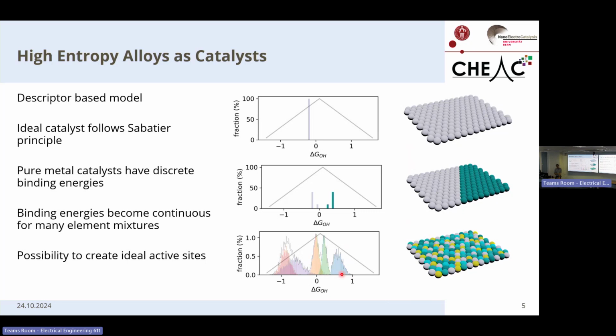So essentially, you think that for designing high entropy alloys for a given reaction, you should always include the state-of-the-art catalyst. Say for oxygen reduction, you should always include platinum. For CO2, maybe gold. Not necessarily. If you get a platinum-free catalyst, you could potentially find a high entropy alloy that has the same activity as platinum, because that's not contradicting the constraints that we have. But they will not be able to rival a binary platinum catalyst in terms of activity. If the target is to have the most active catalyst, you need to stick to a platinum-based catalyst. If you want to have something cheaper on the market, well, maybe there is a chance. And the only way to know it is to study it.